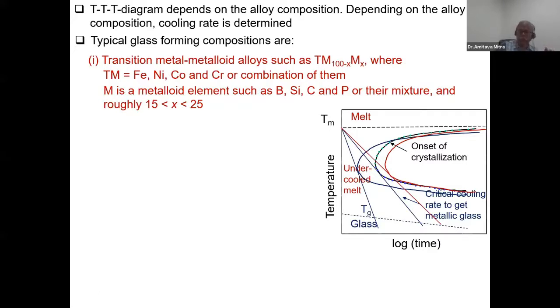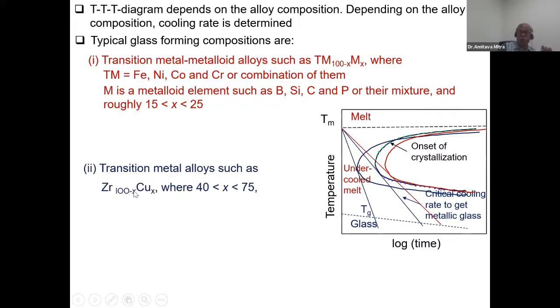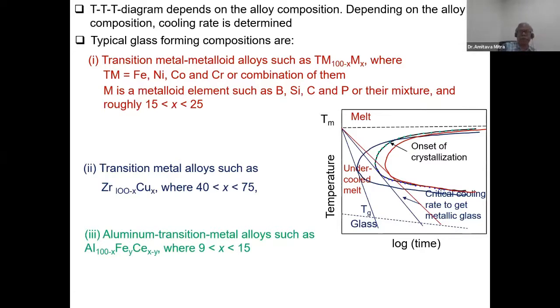There are other types of compositions also possible, such as zirconium and copper based alloys, where copper should be around 40 to 75%. And there is another set of compositions through this technique, the aluminum transition metal alloys, such as aluminum-Fe-X, where X is between 9 to 15.